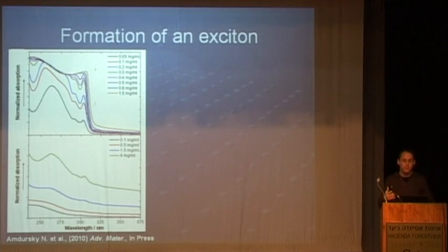So we wanted to further study the whole mechanism of the creation of the quantum confined state and also the formation of the exciton. For that I went to hydrogel, also the spaghetti-like peptide nanotubes, which I showed at the beginning of my lecture. In the hydrogel system, I can play with the concentration. At low concentration, I don't receive any hydrogel at all, and as I increase the concentration, I receive the peptide nanotubes and the hydrogel formation.